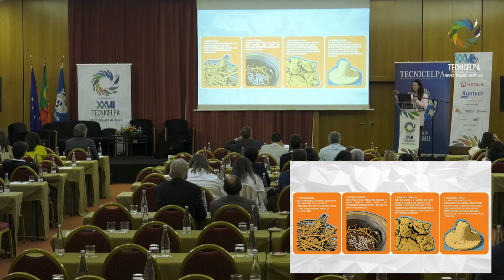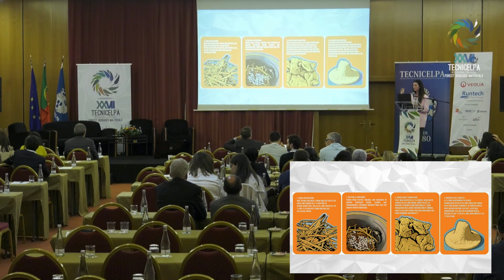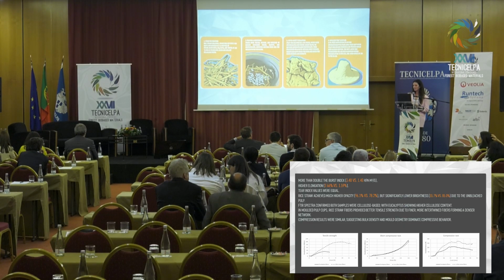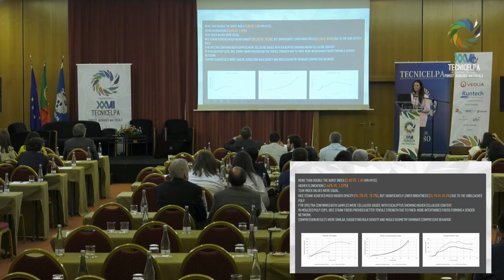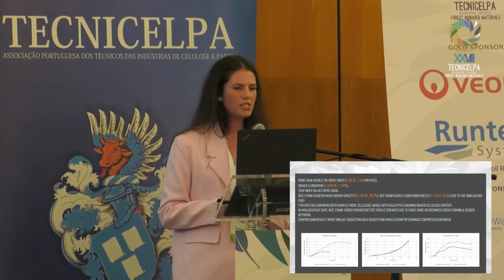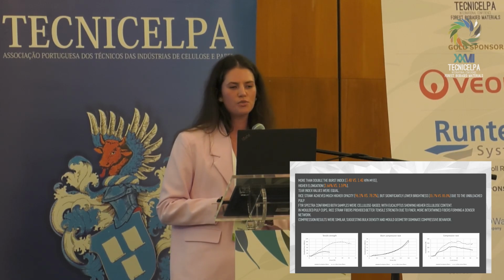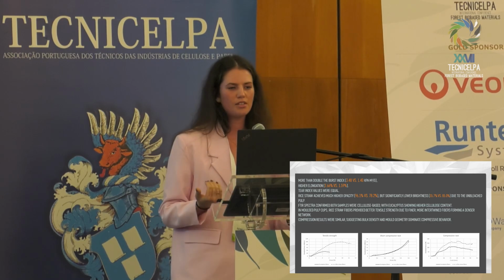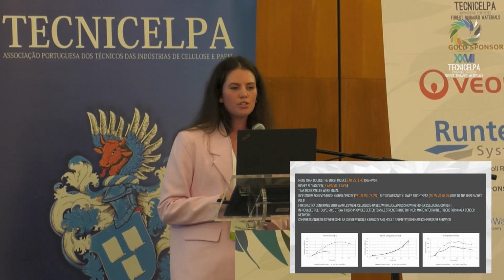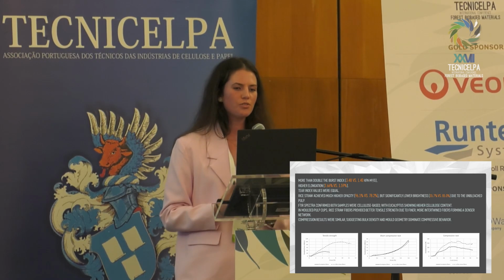I have passed around some of these molded pulp cups. One is the one I mentioned, 70-30, and the other one is made 100% only from rice straw fibers. Okay, more than double the burst index was seen with the rice straw fiber sheets, and along with the higher elongation, the tear index values were equal with the eucalyptus and rice straw fibers, and the rice straw achieved much higher opacity but significantly lower brightness due to the unbleached pulp.